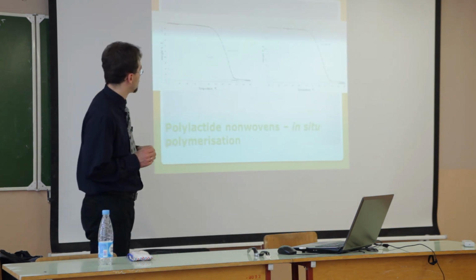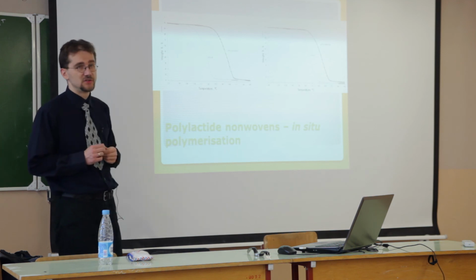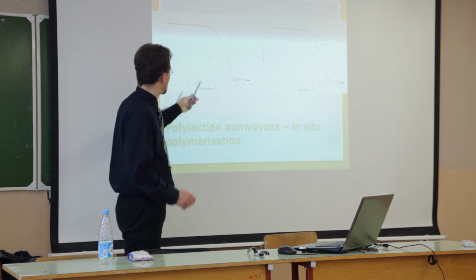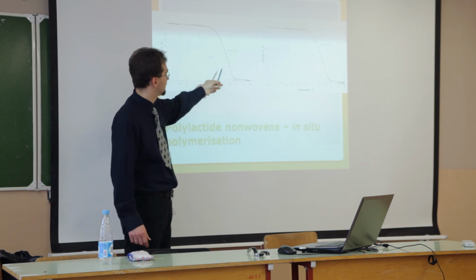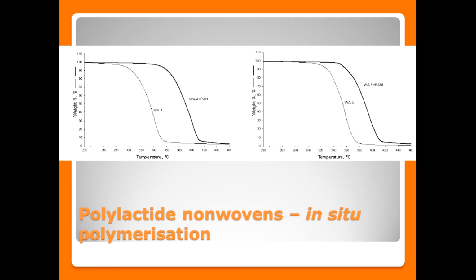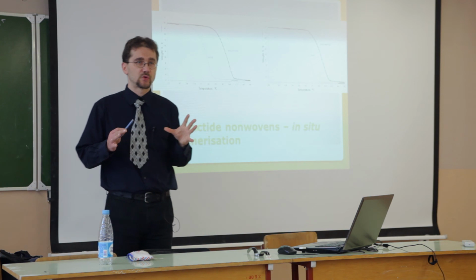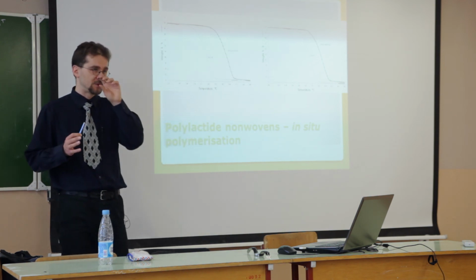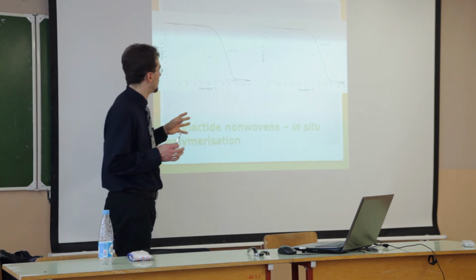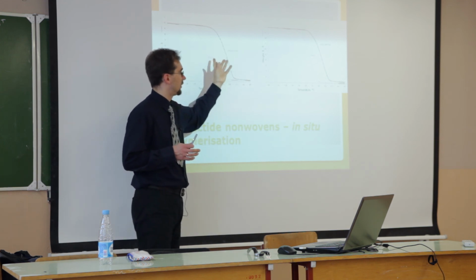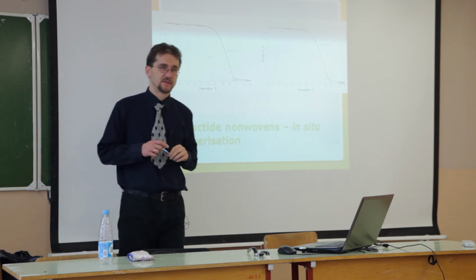Here I would like to show you again the TG curves. Here is unmodified material, and here is material with deposited polyaniline on the surface. We can see the difference is more than 100 degrees. It is, of course, not one macromolecule layer like in the layer-by-layer technique, so we can expect some changes, but this is a very big difference.